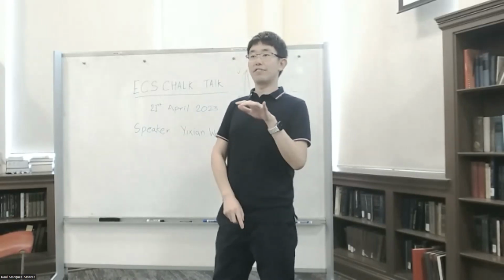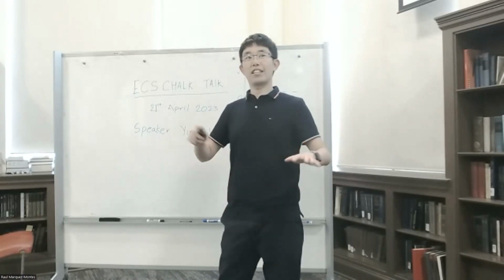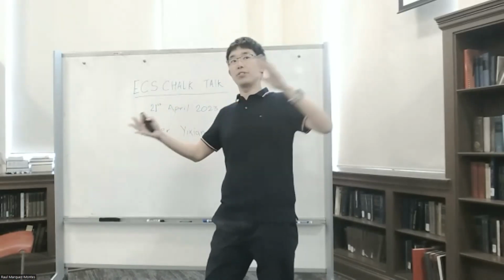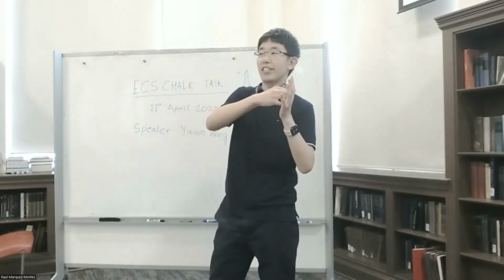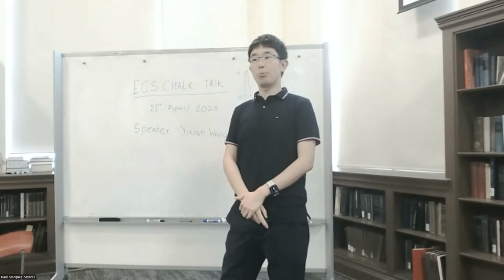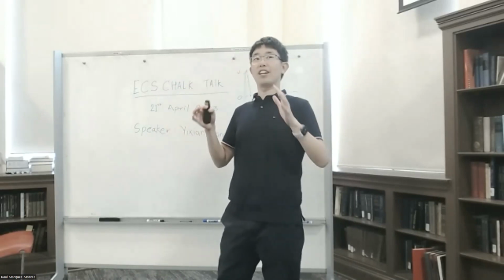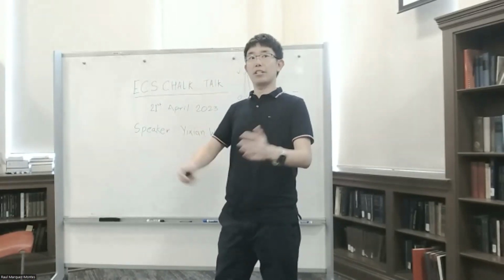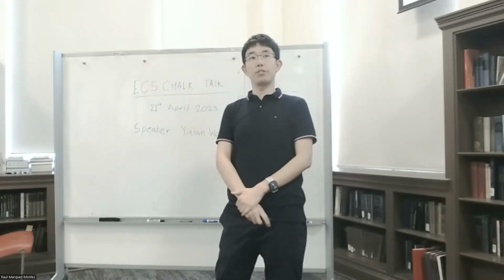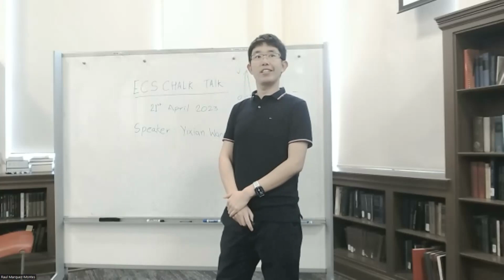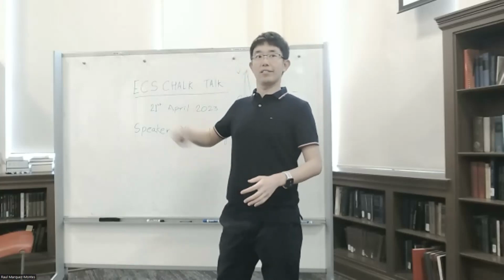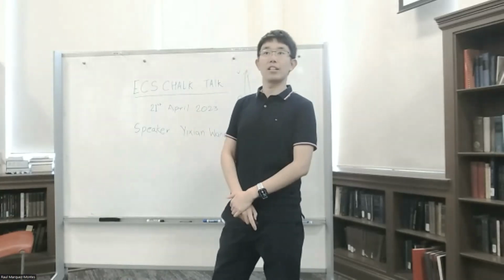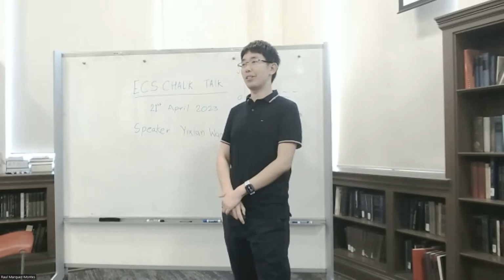So it seems that sodiophilicity or lithiophilicity is not the only factor that affects performance. There's something else, just like I mentioned, the chemical affinity of those structures to your backbone, whether it's strongly bonded or not. And there's also something called work of adhesion, depending on the adhesion of those materials to your current collector, and the adhesion of sodium on the surface of those materials. So it's very complicated, and I hope with more work done by simulation and experiment, we can give a clearer answer about why tellurium turns out to be the best.